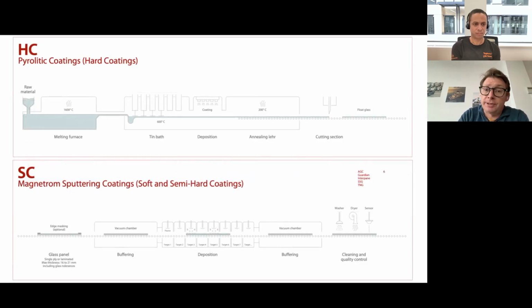And as part of that float process, they also may have coatings on. And when the coating is applied when the glass is hot, that's a pyrolytic coating, and that's what we call hard coatings. And they're called hard coatings largely because they're very robust and they're resistant to scratching. But because they're put on in the inline process, the choices are more limited than the soft and semi-hard coatings, which is a secondary process, which is done in a magnetron, where metals are vaporized and are deposited on the glass. And these coatings are often to do with light transmission, energy transmission, to sort of handle the environmental factors.